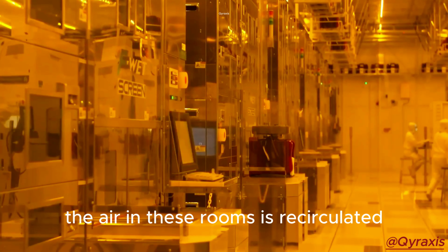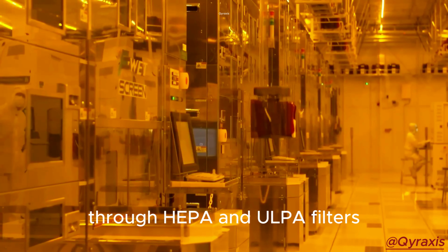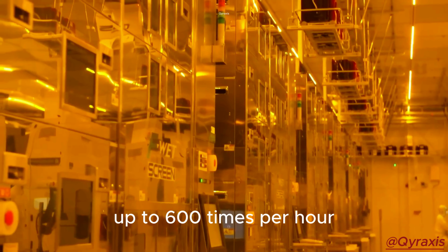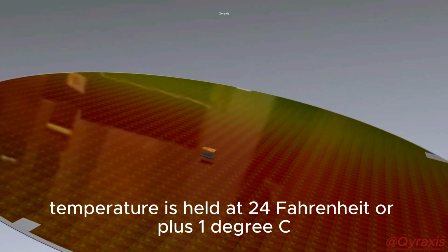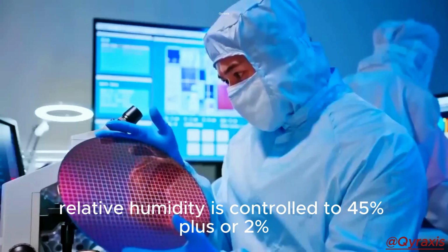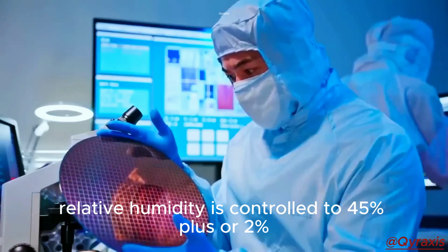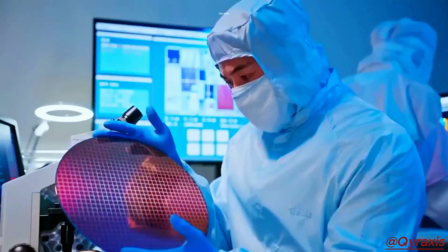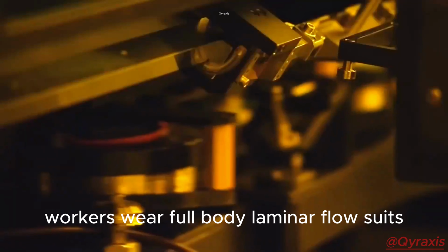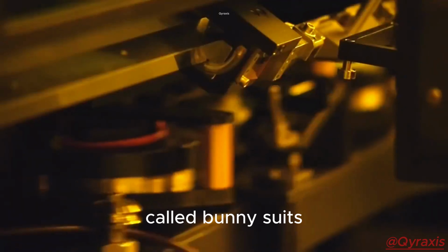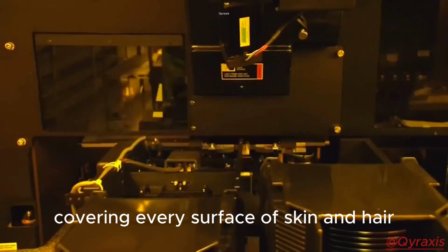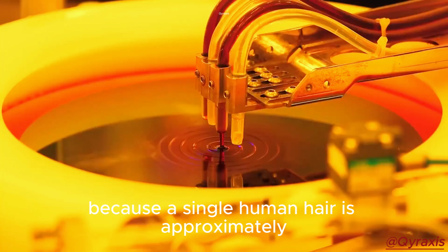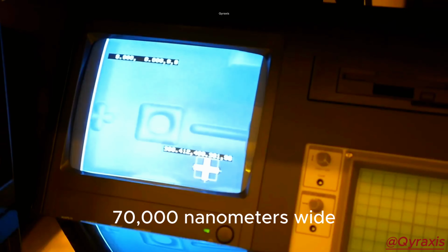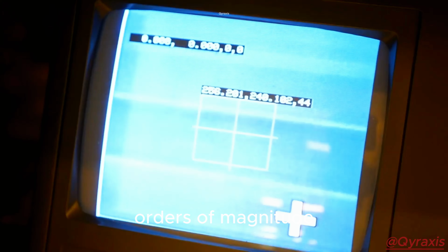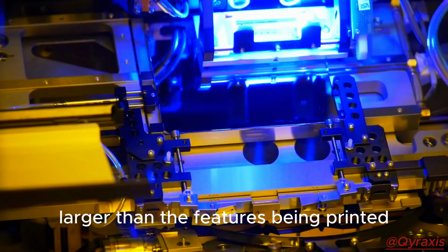The air in these rooms is recirculated through HEPA and ULPA filters up to 600 times per hour. Temperature is held at 24 plus or minus 1 degrees Celsius. Relative humidity is controlled to 45%, plus or minus 2%. Workers wear full-body laminar flow suits, called bunny suits, covering every surface of skin and hair, because a single human hair is approximately 70,000 nanometers wide, orders of magnitude larger than the features being printed.